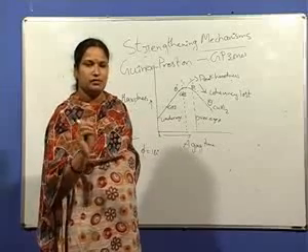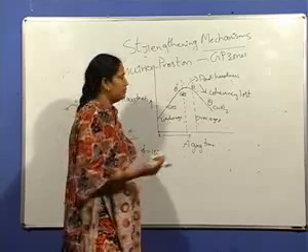Initially, during aging, GP1 zones form, which are small clusters of the solute atoms, which contribute to strengthening because of the lattice strains. With still further increase in aging time, these copper clusters grow in size and form theta double prime, where the strength or the hardness further increases, also known as GP2 zones, because of more lattice strains that are created.